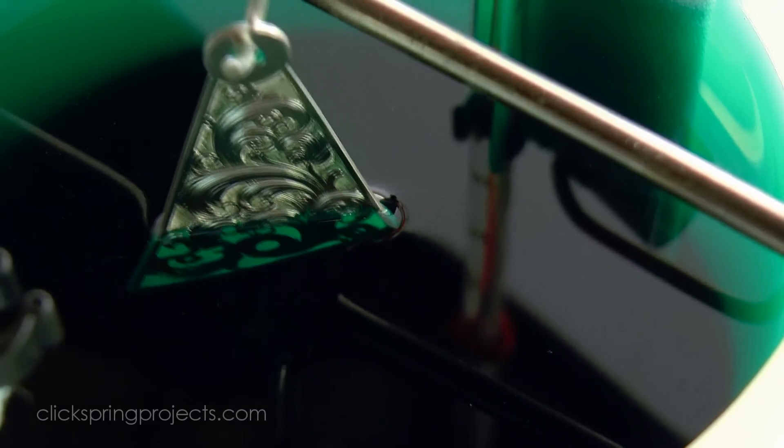This problem is solved by pre-plating the surface with what's known as a diffusion barrier, most commonly using either nickel or palladium. My testing so far is with the cheaper of those two options, nickel.